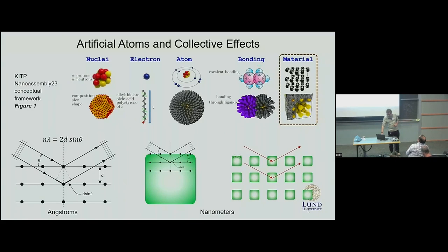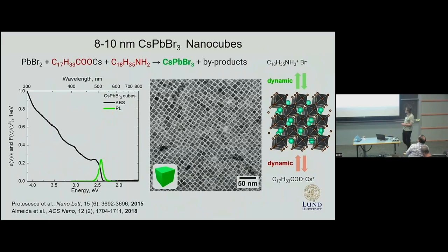So the materials or nanoparticles I'll be talking about are the cesium lead bromide 3 nanocubes, which we make by the hot injection method, by combining lead bromide with cesium oleate in the presence of other surfactants. They appear as fairly uniform cubes in transmission electron microscopy images. The small black spots you see are lead zero, formed as a result of beam damage.